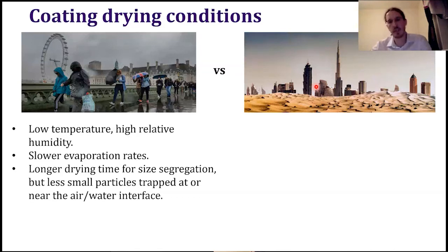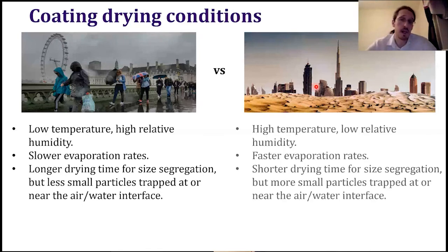On the other side, if we are in the desert, we have high temperature, low relative humidity. And then drying will be much faster. In principle, you have shorter time for size segregation, but your air-water interface will go really fast, and it might trap more particles and improve the stratification. But we want something that could hopefully work for both of them.